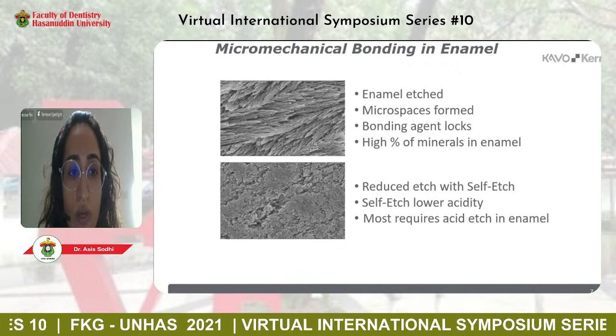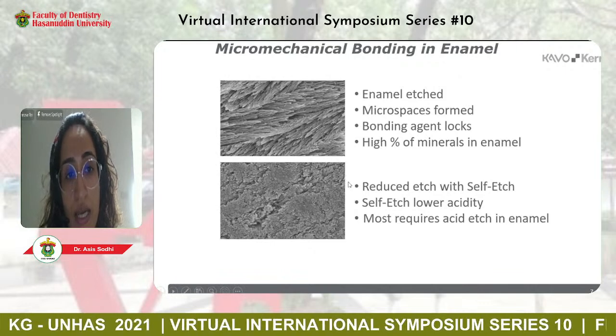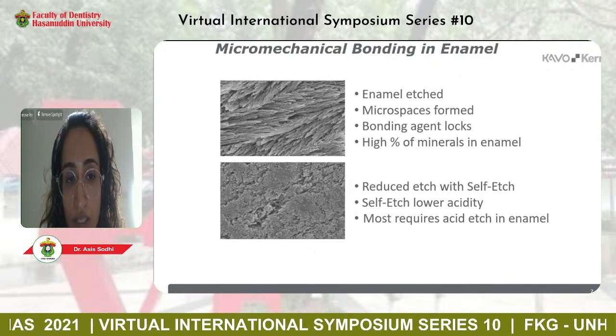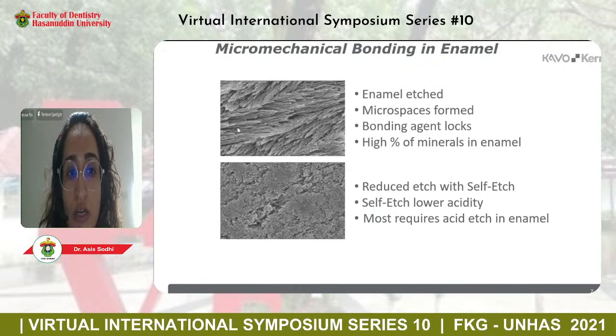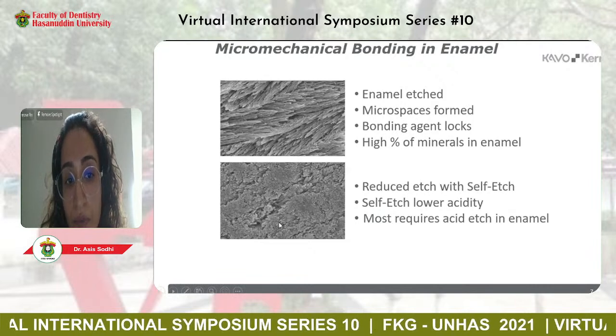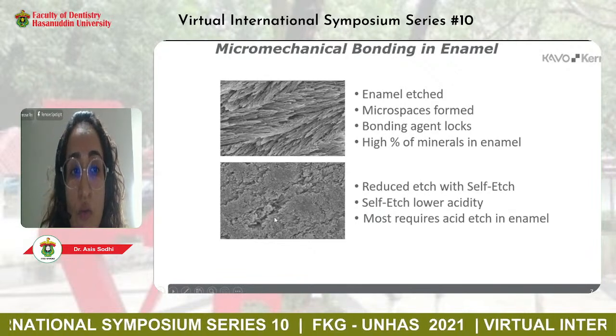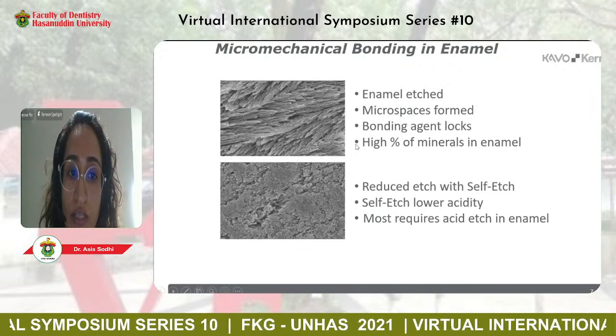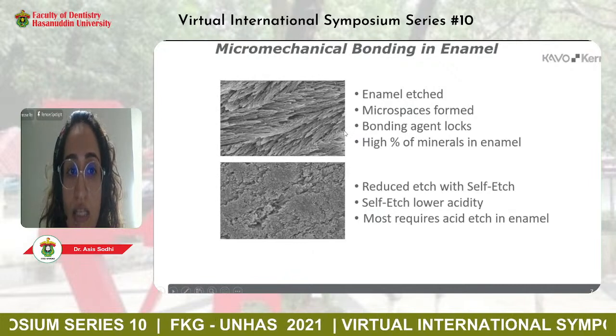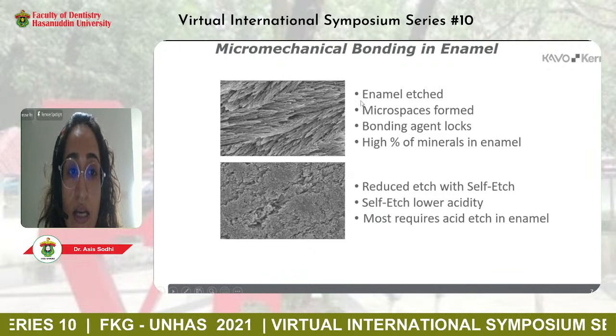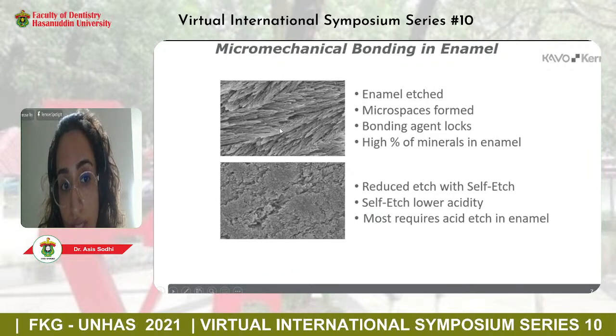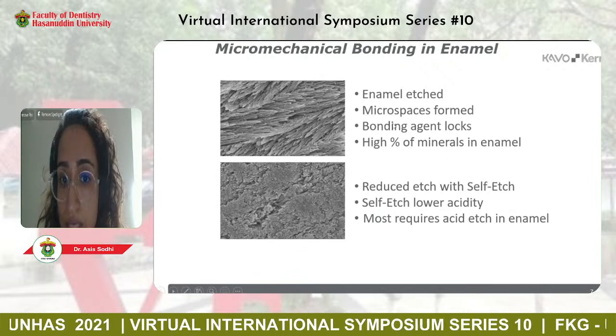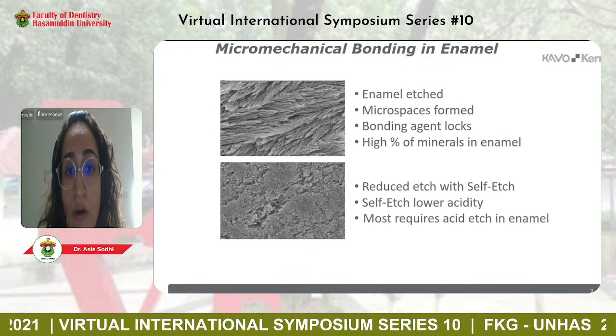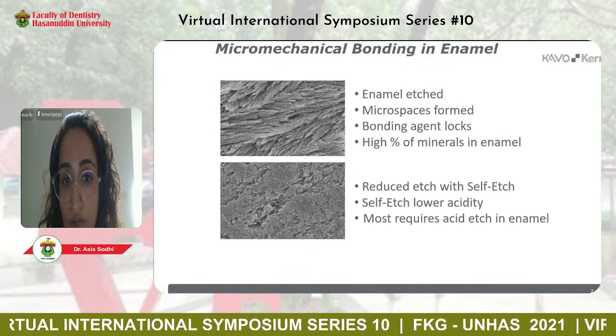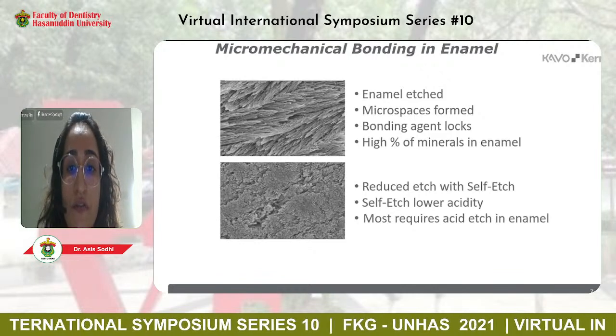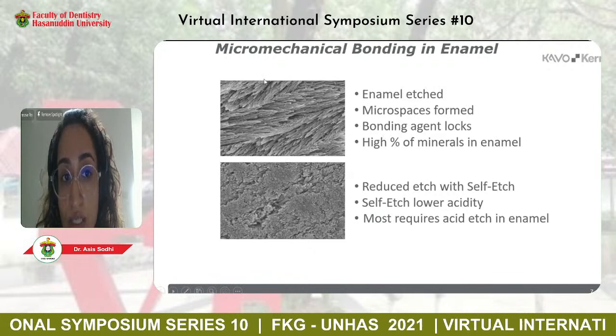These are SEM images. When you look at these images, you can see the image on the top is really a pattern that is more aggressive. It's very visible to you. You can see it's much more aggressive than the pattern that you see at the bottom of the image. So why do we have a more aggressive pattern? That's actually an end result of using a strong acid. So as a part of enamel etching, when you're using a strong acid, that is the kind of etching that you get and the pattern that is formed on the surface. So there are microspaces that are formed. Following this process, when you apply the bonding agent, it is able to lock itself in place, and a high percentage of minerals in enamel is removed as a part of the enamel etching, which you can see in the first image.